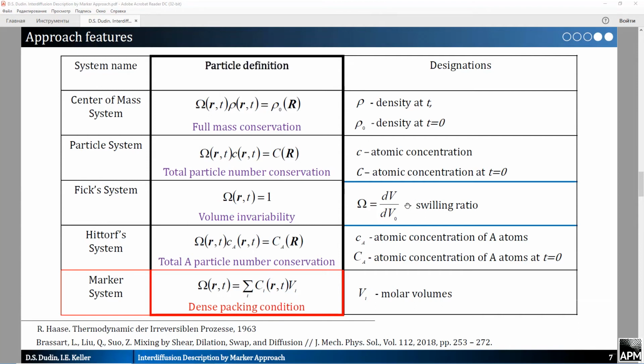Here and further on, the large omega is the ratio of an actual macroparticle volume to the reference one. There are 5 main definitions of the macroparticle, depending on the selected systems. The first one is the center of mass system. Here, the total mass in the macroparticle volume doesn't change with time. The second system is the particle system. Here, the total number of particles in a macroparticle volume doesn't change with time.